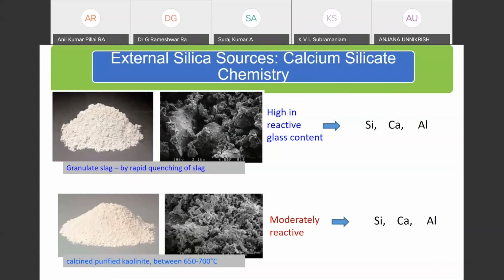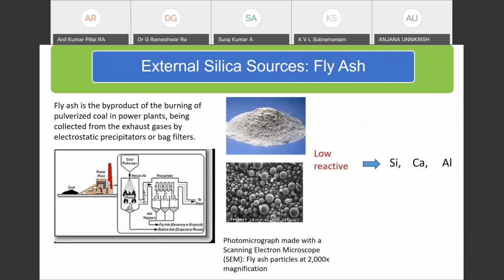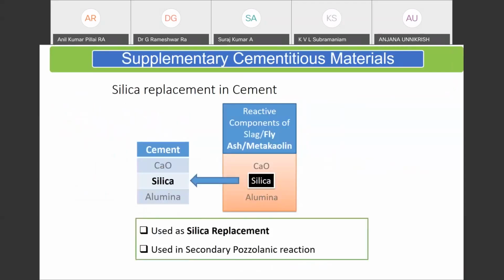Metakaolin is something that we produce by calcining clay. We calcine clay at 650 to 700 degrees Celsius. It's moderately reactive, but again contains silica and calcium. Therefore, we are able to use it as a clinker replacement. But coming to fly ash. Now, fly ash is a waste material that is produced by burning coal, and it's a grayish powder. Fly ash is a low reactive material, but it contains silica and calcium. So if we look at silica replacement in cement, the way it works is that if I look at cement, I have calcium, silica, and alumina.